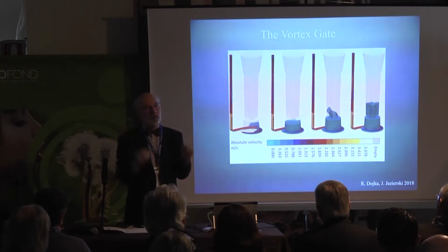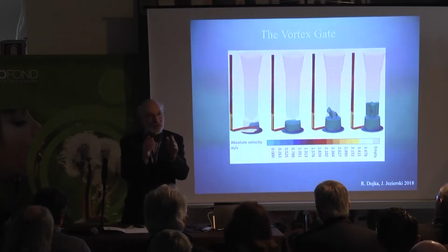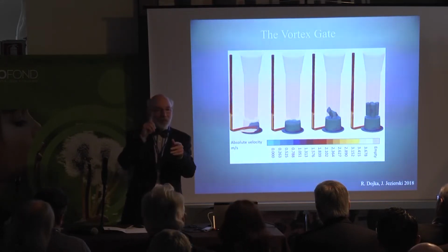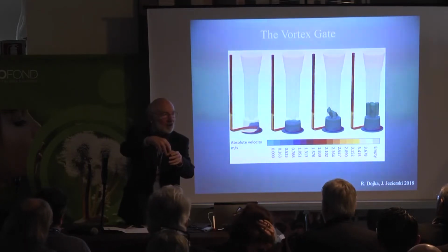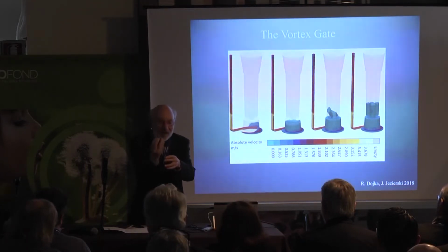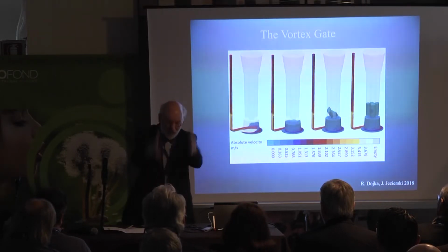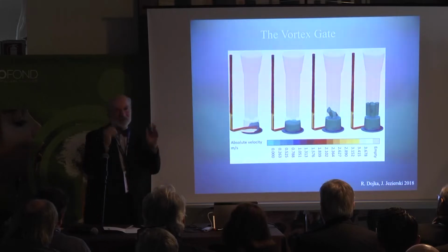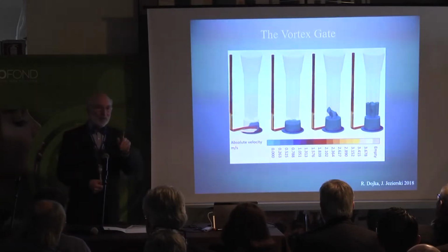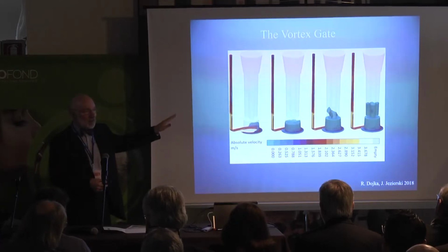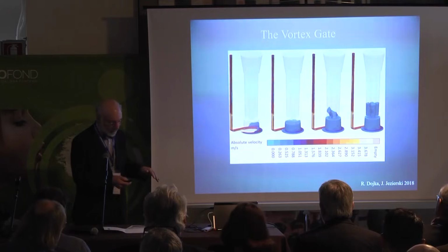It was terrible. The reason for it being really bad was that the bubbles were centrifuged into the center and they couldn't escape. And so every bubble in the system went through into the casting and ruined the casting. Useless, okay? Now, the bubbles were the big problem. So there was that beautiful gating system ruined because it couldn't deal with bubbles.